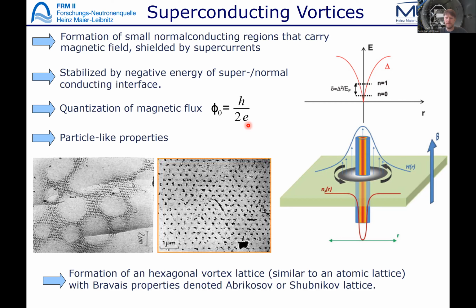This was found by Abrikosov, that these vortices arrange in a regular 6-fold lattice. We see that here in the decoration images, where ferromagnetic powder is evaporated in vacuum, and the powder then sits on top of each vortex. So these vortices behave like particles, they interact. And we can do superconducting vortex crystallography. As we do crystallography on condensed matter, we also can do crystallography on superconducting vortex matter. And this is essentially what Emma has been doing in her thesis.